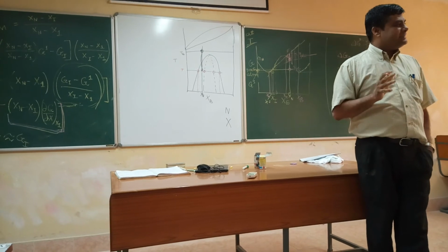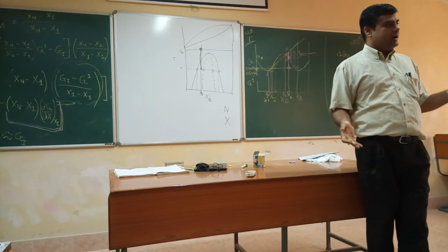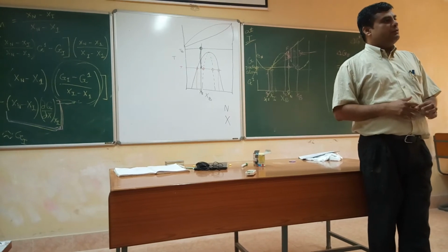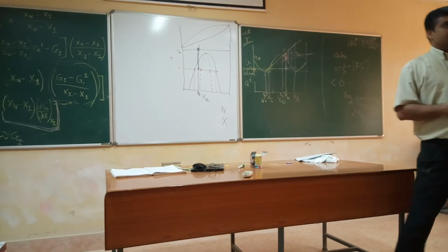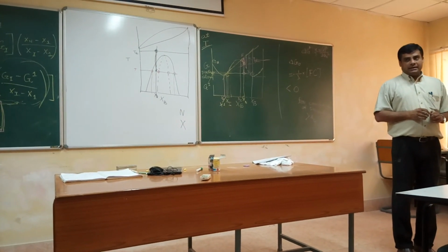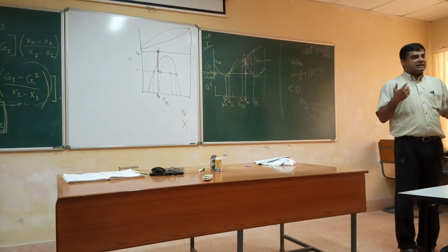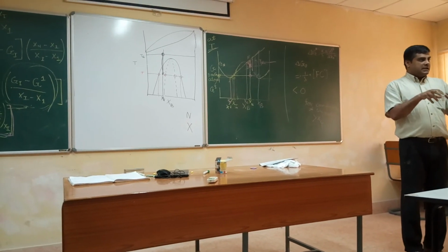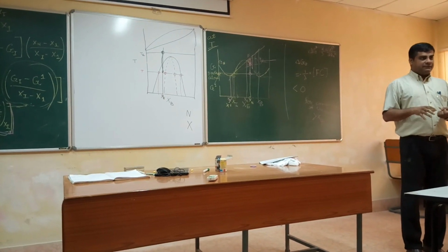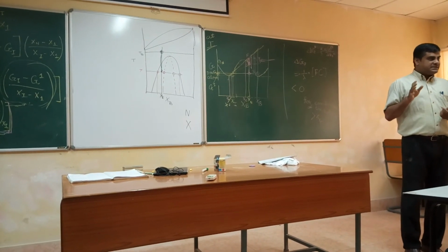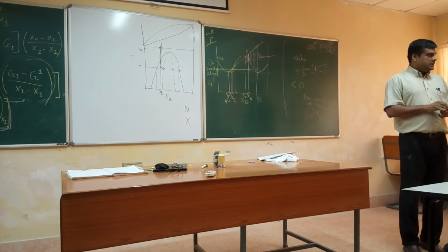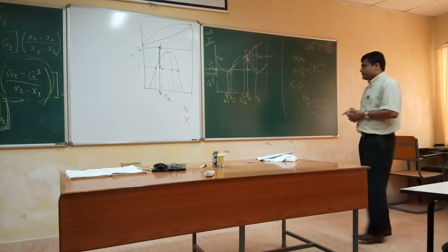You want the mod value of negative delta GV to be high, but you want gamma to be low. But gamma also is composition dependent. For a case like this where the structure is the same, the interface may form a coherent or semi-coherent interface. Their interfacial energy is dependent on the composition of both alloy and embryo.